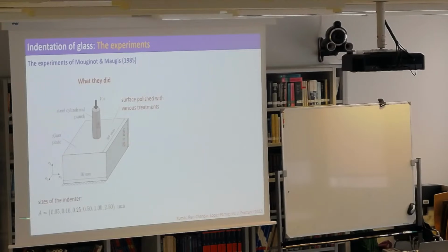All right, so they looked at a bunch of indenters, and these are the sizes, and the experiment was driven in displacement at this rate, which is quasi-static. And this is what they observed invariably. This is a cross-section of what's happening. They saw that they nucleated a crack, which we can call a ring crack, at a given distance from the indenter, and more or less vertical, and after some height, we call it h, it turned into what's called a cone crack. So nucleation, propagation. That's what they saw.